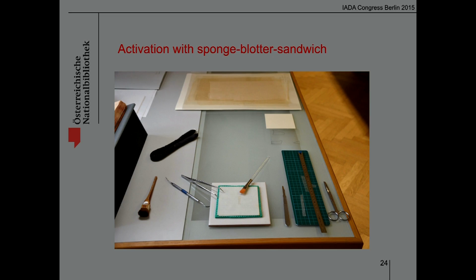The papers were coated with a mixture of 3 parts gelatin, Gelita photographic gelatin, type B, 2.5%, and 1 part Klucel G, 2.5% in water. The adhesive mixture was applied on a silicone mat to reduce gloss. The pre-coated papers were activated by the sandwich system, which consists of a kitchen cloth, humidified with water, and a blotting paper on top, as you can see on the slide.